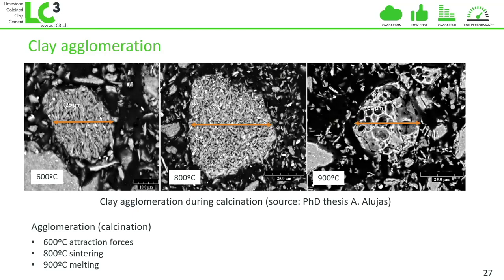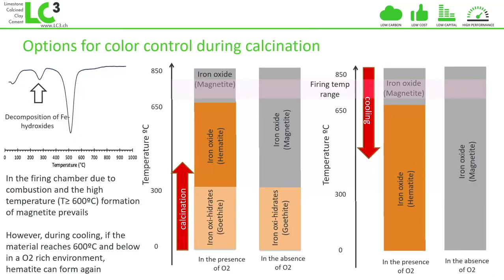Because in these agglomerates, you can trap water. And this is further to the electrical charge and the other things that are taking place. You also have to deal with it. One of the strategies that companies are using is firing at higher temperature to reduce the water demand. But then when you do so, you're compromising the reactivity of your material.